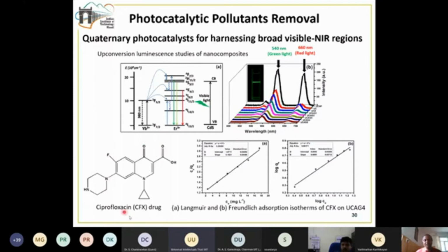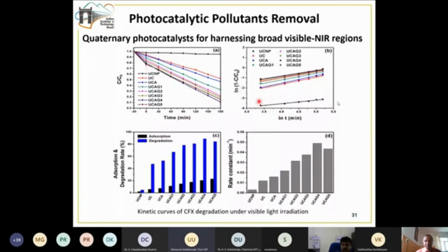And first we did the adsorption studies, how this drug or the pollutant is adsorbing. Adsorbing means it's sitting onto this material. Then we did this adsorption study, and we fitted the adsorption data using Langmuir and Freundlich isotherms, and we found that the Langmuir isotherm fits the data better. Then we did this photocatalytic pollutant degradation experiment, first under the visible light. Visible light because it has cadmium sulfide, which is a visible light active semiconductor. It also has the gold nanoparticle, which has the surface plasmon resonance effect under the visible light.